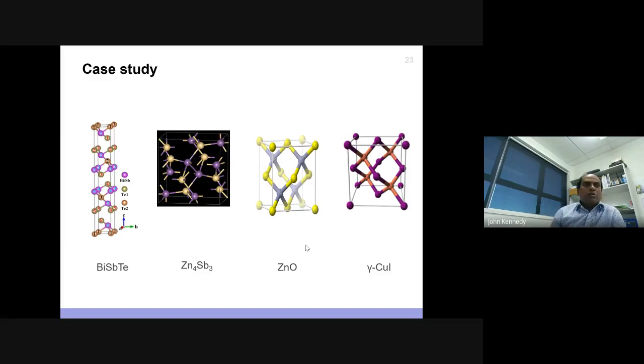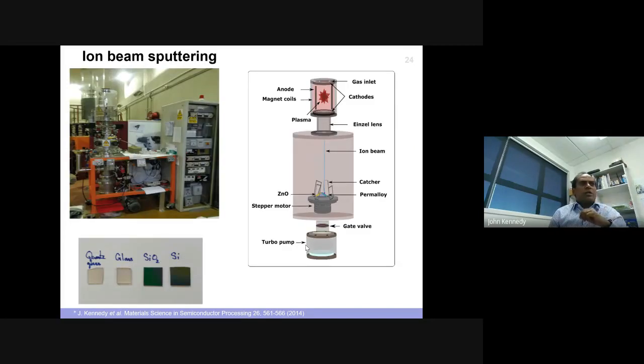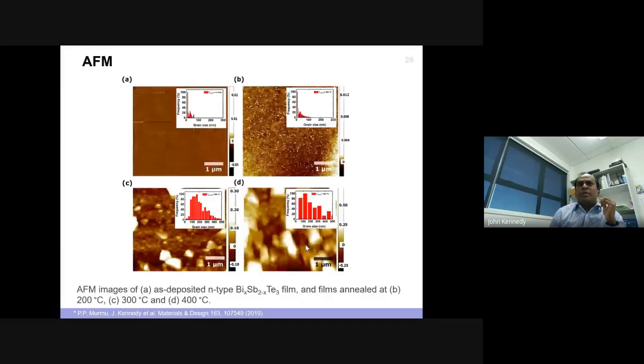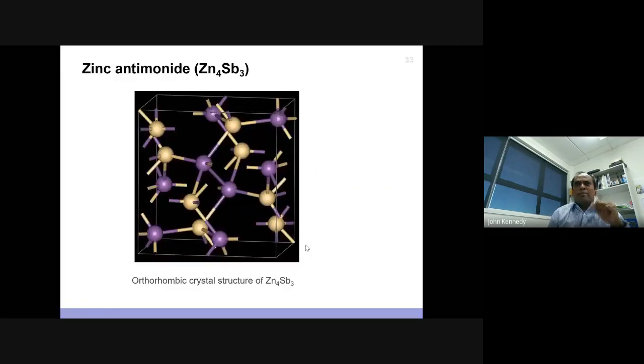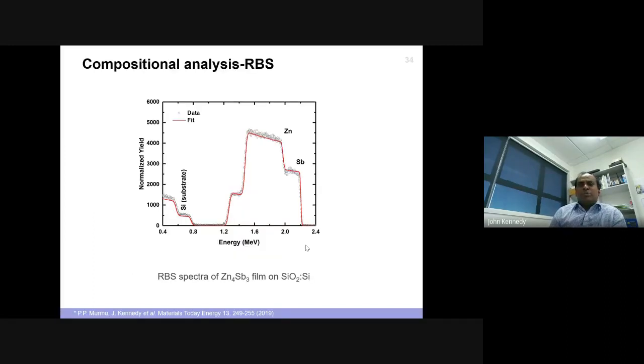So we look at a bit more. The next material we looked at is zinc antimonide. That's again an orthorhombic structure, which is another interesting material, which we made as powder and films. In this case I'm presenting a zinc antimonide film, with composition analyzed by Rutherford backscattering spectrometry, where we can measure the thickness.